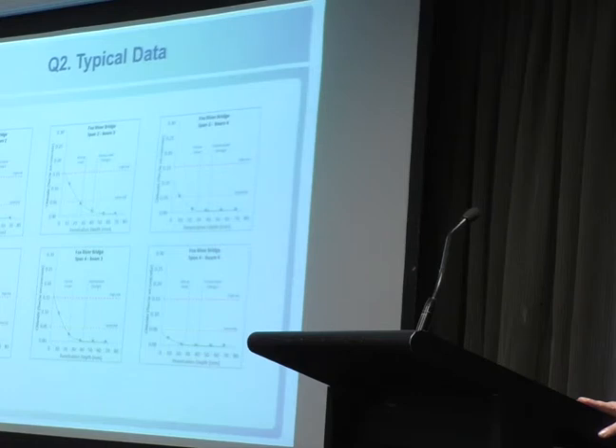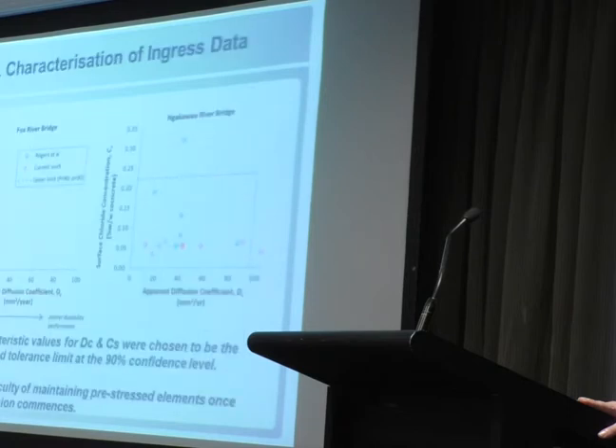Again, the level of chlorides aren't extreme, but that really comes back to the choice of what threshold you choose. I'll go into that in a little bit more detail. And just to choose values for characterization, we somewhat arbitrarily said we would use the 90% upper one-sided tolerance limits at a 90% confidence level for the measured diffusion coefficients and surface chloride concentrations. That was just intended to reflect the fact that you are dealing with pre-stressed elements. You don't want any loss of section through corrosion, so we tried to set the limits fairly conservatively.